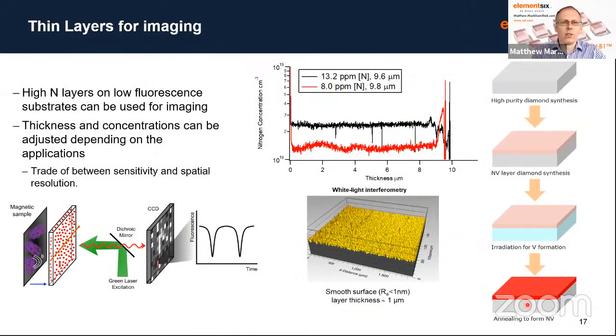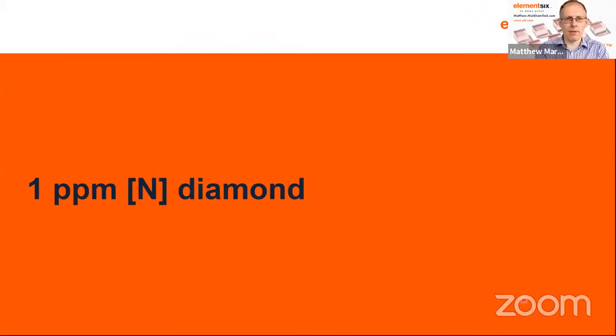I'm not going to talk about this in too much detail, but we can also apply this process to producing thin layers, and I'll talk a little bit about why that's useful later. But basically, you then end up with a process where you have this 16 ppm process on what is a high purity material. So we take a high purity substrate, grow this layer on top, irradiate it, and then have this diamond that can be used for wide field imaging. I'll talk a little bit about that later with some case studies.